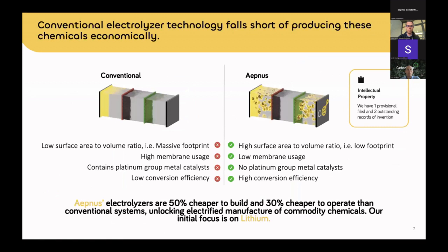There are a number of things that we do better than conventional electrolysis systems. Namely, we minimize the use of platinum group metal catalysts. We have a special secret sauce ingredient that allows us to enhance the catalytic surface area of our reactors, which means that we can make reactors that are smaller in footprint, so they use fewer membranes, they're more efficient and cheaper. And at scale, we anticipate that our electrolysis systems will be about 50% cheaper to build and 30% cheaper to operate as compared to the traditional thermochemical caustic leach flow sheets that I showed earlier that require sulfuric acid and sodium hydroxide chemical inputs.